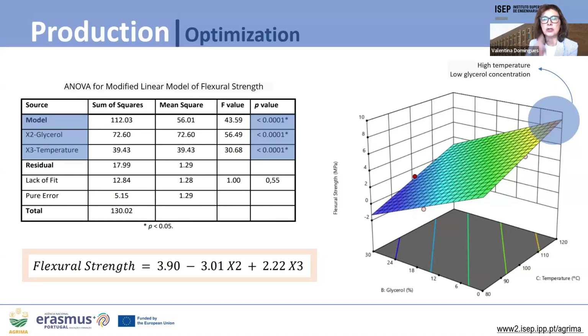Considering that the quadratic model didn't show a very good adjustment to experimental values, a linear model was done without the variables that didn't show considerable influence. Based on ANOVA analysis of variance results for the modified linear models of flexural strength, only the glycerol and temperature show very strong evidence of the response, indicating that glycerol content and temperature play crucial roles in flexural strength. The model itself was highly significant, providing very strong evidence of the fit model. So we obtained this equation to determine the best biocomposite to obtain the best flexural strength.